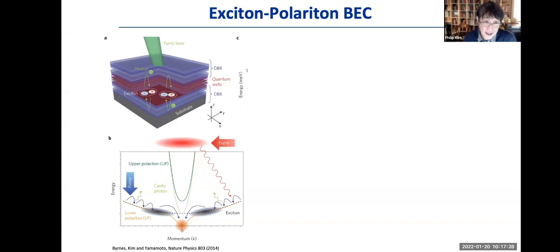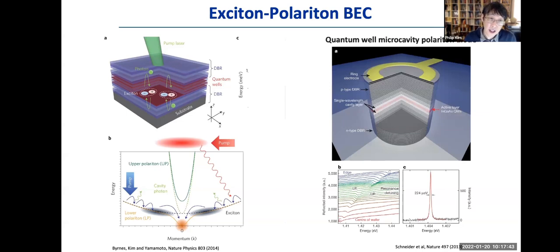And if you just control the density and the temperature, this exciton polariton as a composite boson can condense into the exciton condensation states. In fact, you don't even have to use light to create this exciton polariton condensation. You can excite the photons by lasing this quantum well, and through this lasing effect, you can combine this exciton polariton, electrically exciting the system. All of these things create this exciton polariton condensation state, which is quantum coherent. So this is one way you can create another coherent light source.